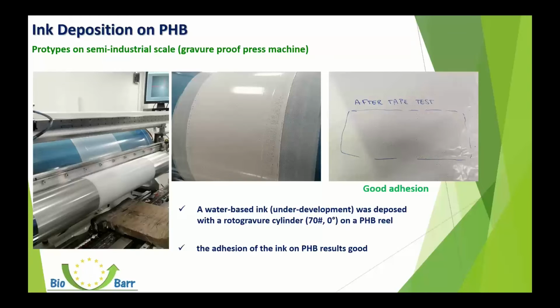In this case, an under-development water-based ink was deposited with the rotogravure cylinder, and also in this case, the adhesion of the ink on PHB is good, as it passes the adhesive tape test after 24 hours.